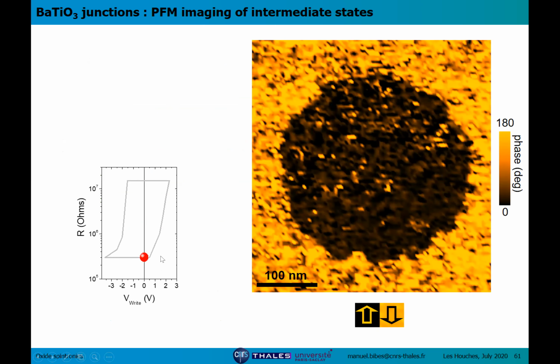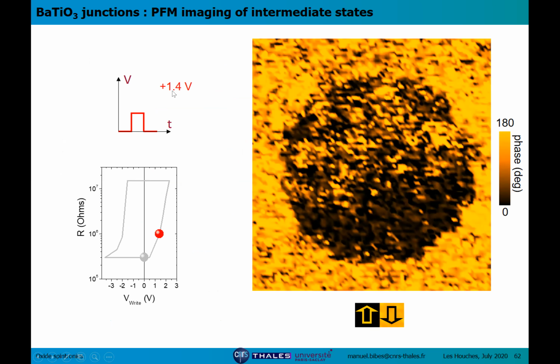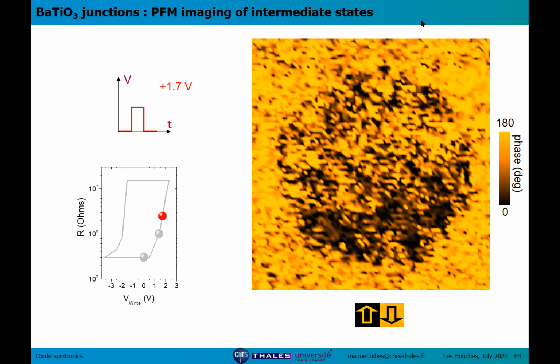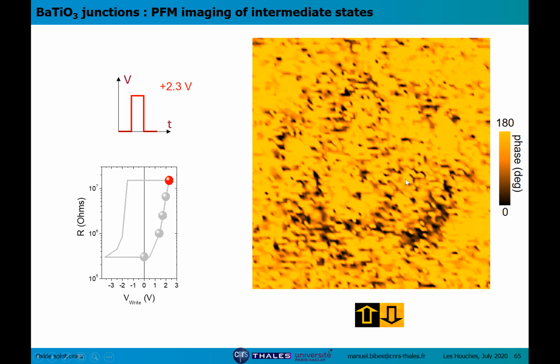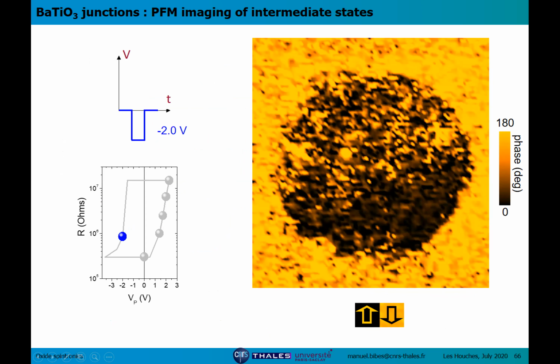And the results are shown here. This is the typical resistance versus voltage curve. And here we are in this state where the resistance is low. And this is the domain configuration where the polarization is pointing up. When we apply a voltage of 1.4 volts, we see that we have the nucleation of down domains, and eventually these down domains saturate the junction, and we have a fully reversed state, and the resistance reaches a maximum value, and we can come back to the initial state.